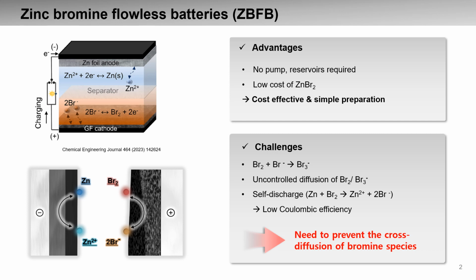However, a critical challenge for this system is the problem of self-discharge, which usually results in low Coulombic efficiency. For instance, as I explained, Br2 can be formed at the positive electrode during the charging process, and this Br2 molecule can combine with additional bromide ions in the electrolyte and form polybromide such as Br3-.